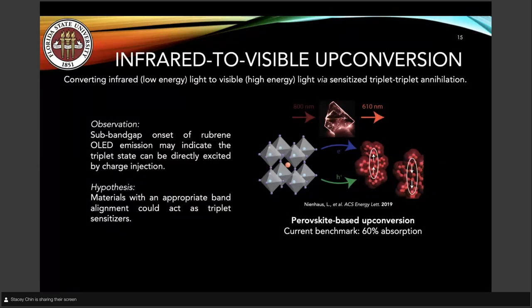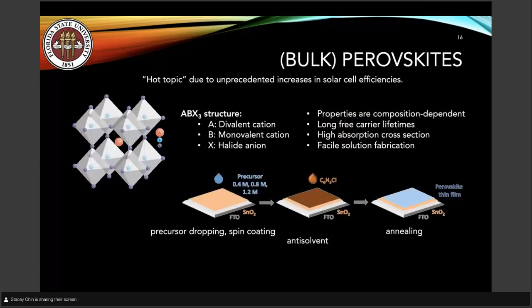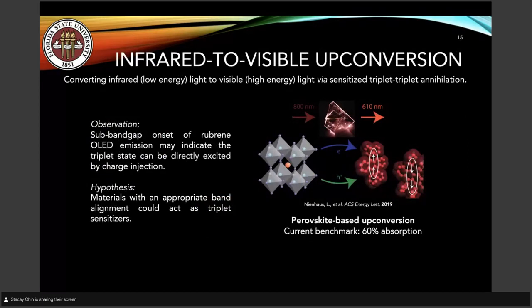So I was inspired by two things to do this work. First of all, there are reports of a sub-band gap onset of rubrene emission in OLEDs. And so this indicates that the triplet state could be directly excited by charge injection. And the other reason I was inspired to use perovskites is they appear to be better at pretty much anything than most other materials have been in the past. And so why not give it a try? And so our hypothesis was that any material with an appropriate band alignment could actually act as a triplet sensitizer.